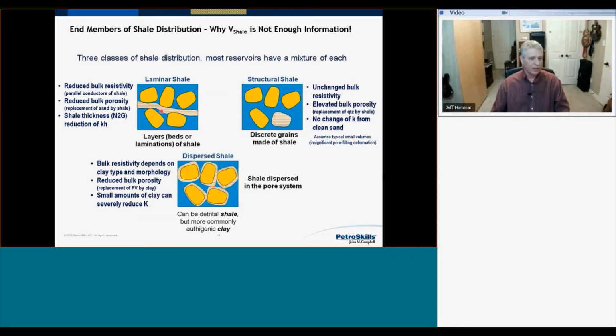So let's look at the effects of having this laminated sequence. We have a sand, these yellow grains, in which we placed a shale layer. To place that shale layer, we had to take out some volume of sand as a layer and insert this shale layer. Doing so has a number of impacts. One, as we mentioned in that previous slide, the shale would be parallel. If our borehole was drilled normal to bedding, then we would have parallel conductors, and it would drop the induction resistivity substantially.